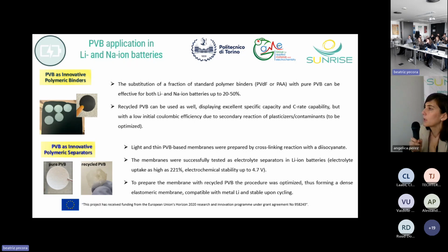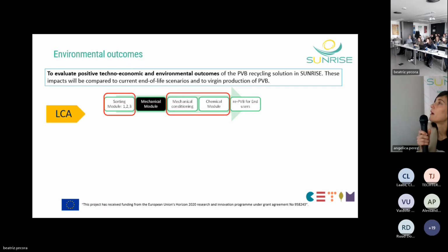And then we have been working to use this recycled PVB. The procedure was also optimized for the preparation of the membranes, forming dense elastomeric membranes, also compatible with metal lithium and with stable cycling. So, there is also work pending for these applications, but results are interesting, and there could be some chance to use recycled polymers in batteries. And that's related to applications.